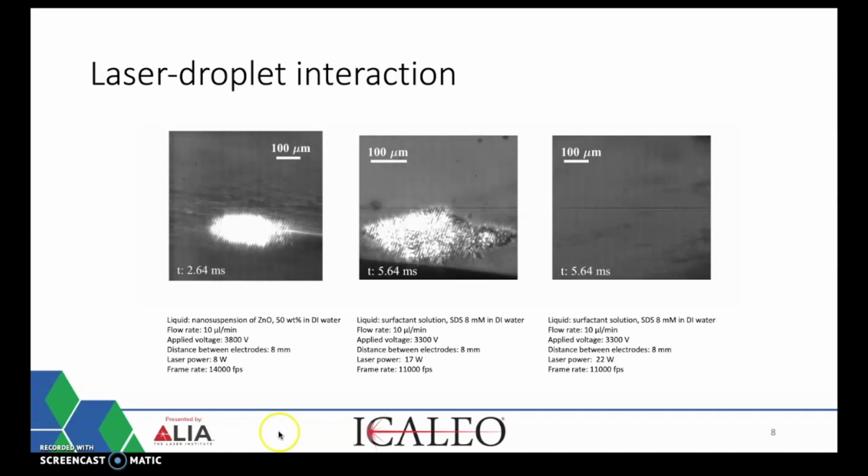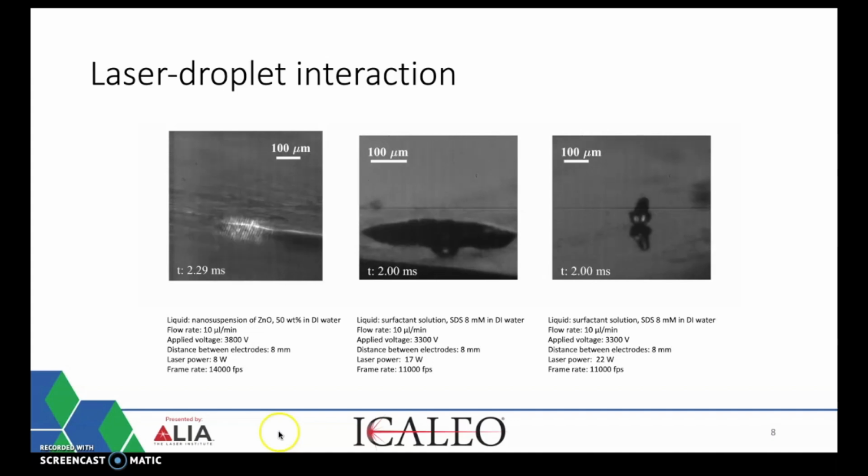In the animation of the center, we can see the interaction of the characteristic cross-section intensity of the Bessel beam and the curved liquid surfaces or ripples. Due to active boiling of the droplet, the fringes that are visible in this animation are visible only during the time that the pulsed laser is on. The brighter spots inside the droplet suggest that the laser beam was refocused by the multiple ripples of small radii of curvature at the surface of the liquid.